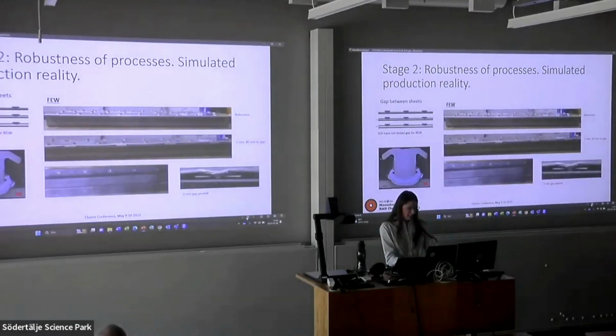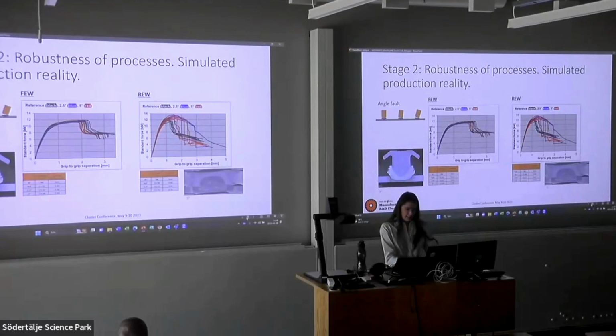We tested gap between sheets, not a problem for friction element welding. We still haven't tested resistance element welding. This we scaled up to the bigger hat profiles, and we saw that we got full pull-out plug failure when we peel tested. We tested angle fault or misalignment of welding electrodes, and we did not really see any impact here on the process robustness.